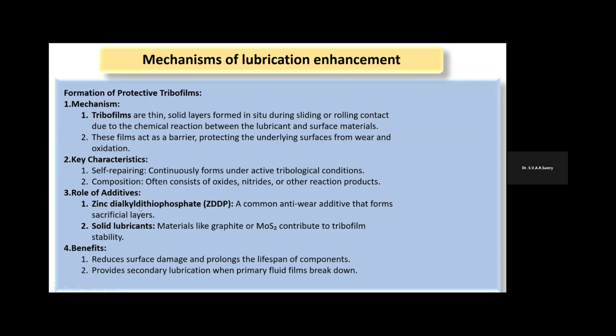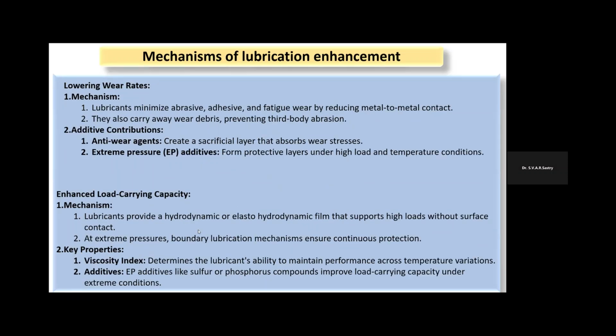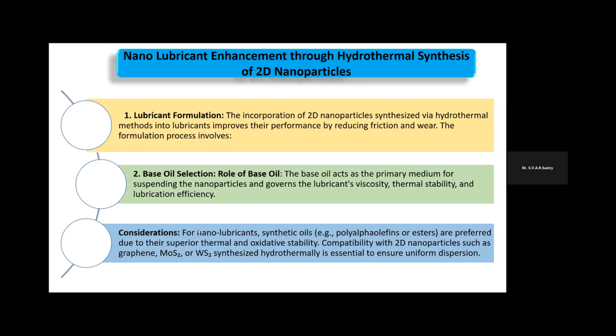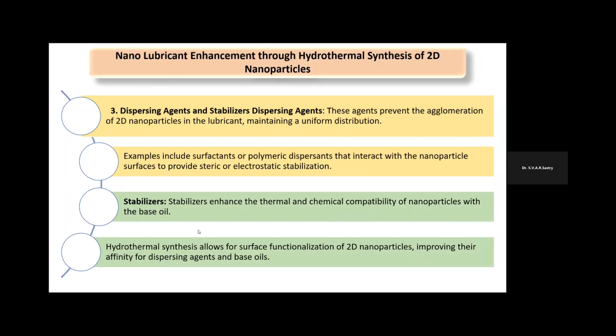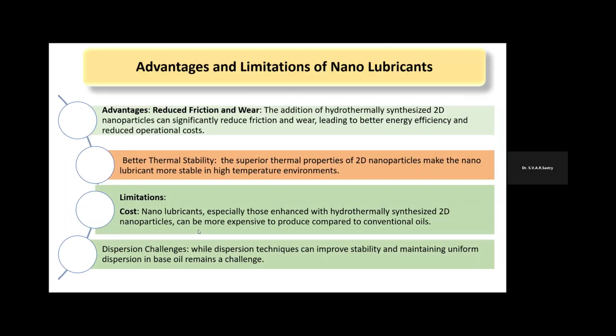We can also use additives like zinc dialkyl dithiophosphate, which can be used as an anti-wear additive and can form sacrificial layers during the lubricant operation. Similarly, you can also use solid lubricants, where materials like graphite or MoS2 can contribute to tribofilm stability. It also lowers the wear rate, increases the performance in extreme pressure and high temperature, and also enhances load carrying capacity. So we just move forward with the further advantages.